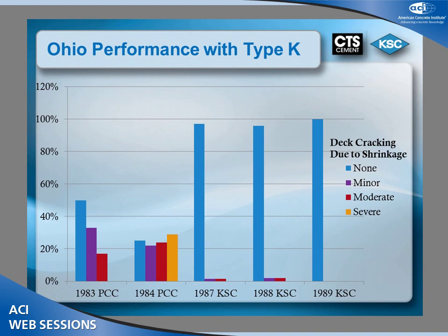Looking at this graphically, if you look at 1983 and 1984, these were when they were doing just the Portland cement study, you can see the various different crack characteristics. They rated them in 4 ways: none, minor, moderate, and severe. And as you can see, in 1983, approximately 50% of the bridges that were done, there was only 6 of them, by the way, had no cracking at this point in the study. However, it looks like we had about 18% that had moderate. There was no severe. In 1984, for some reason, with that same mix design concept with Portland cement concrete, they started seeing a lot of severe cracking, as you can see in this diagram.